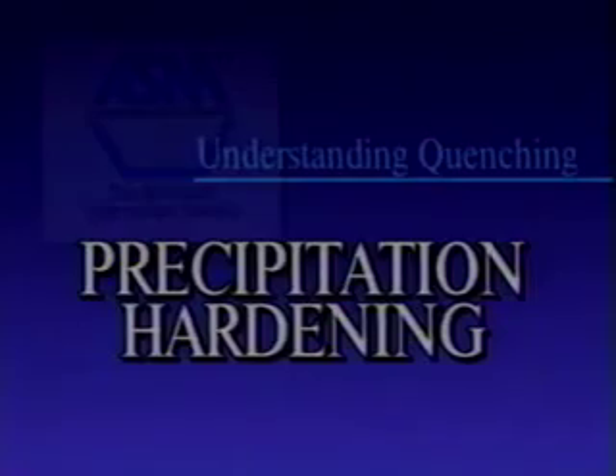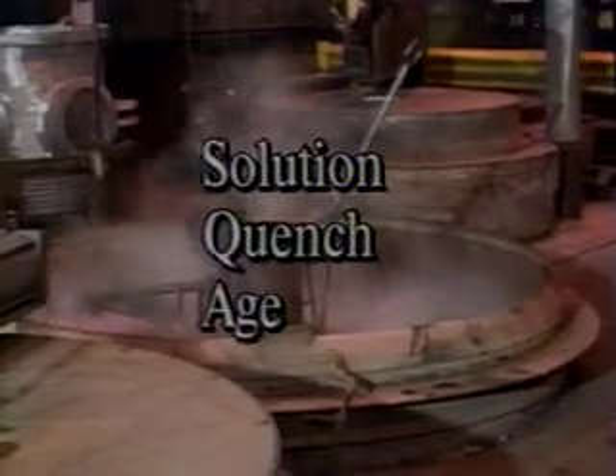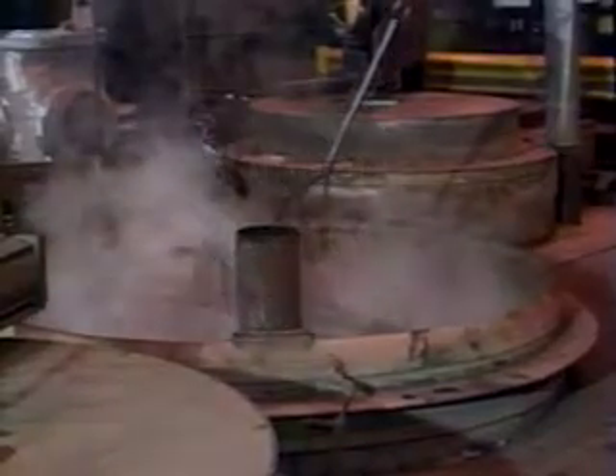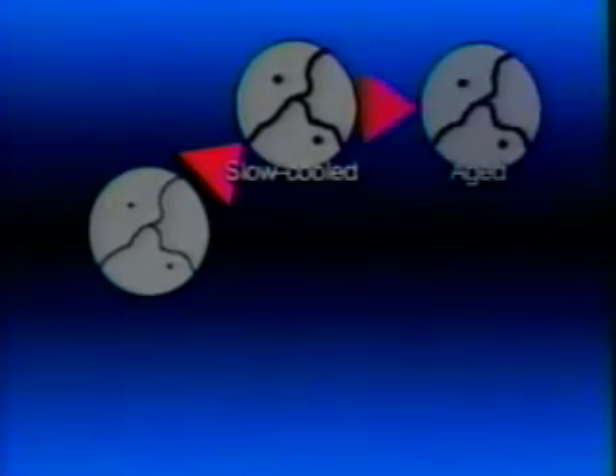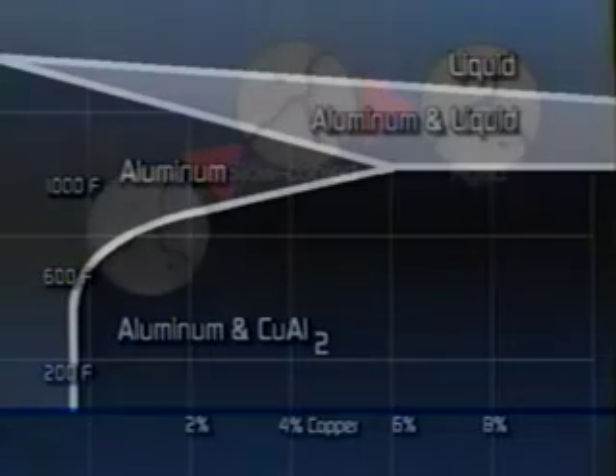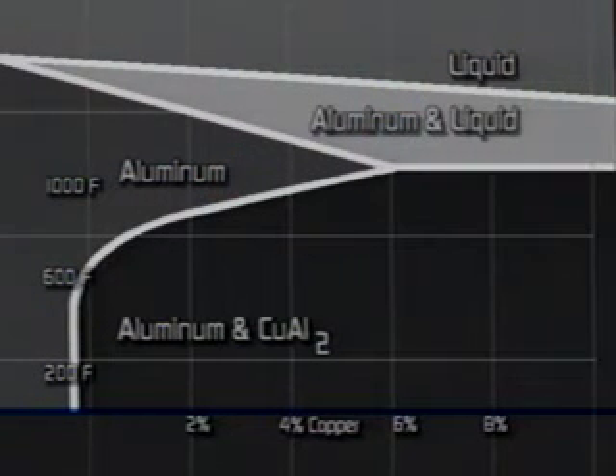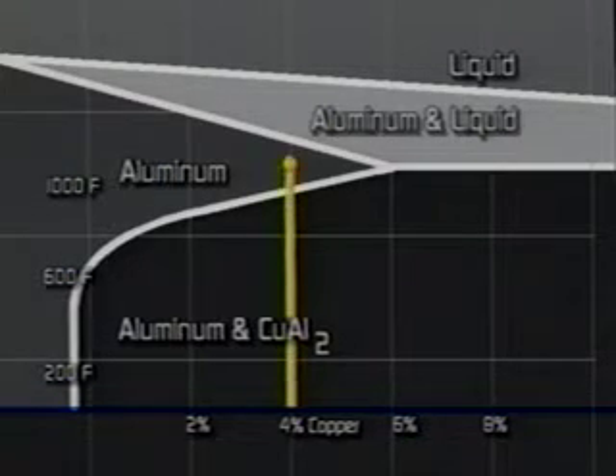Precipitation hardening by quenching. The process of heat treating non-ferrous alloys is basically the same as for ferrous alloys, but the heating for treatment is called solutioning. It might help us understand what can be achieved by quenching a non-ferrous alloy from a solutioning temperature if we consider the aluminum-copper binary phase diagram. Let's consider an aluminum-copper alloy containing 4% copper by weight.